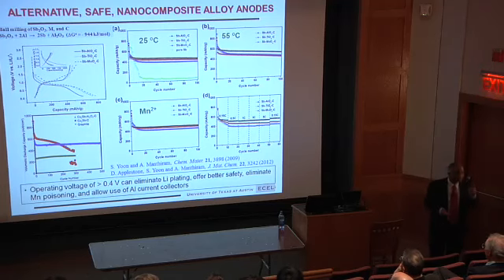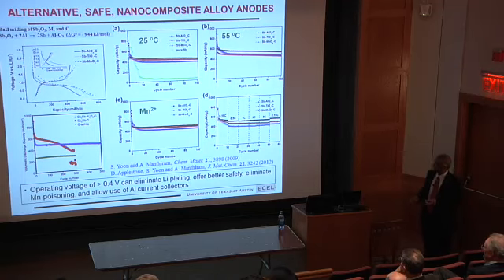But tap density is 2 times or 1.5 times more than graphite. So volumetric energy density will be huge. Right now, this has been licensed by a startup, and they have a NIST contract, and they are working on manufacturing it. Fortunately, not a lot of people are working on that, so you can do a lot of different things with it.